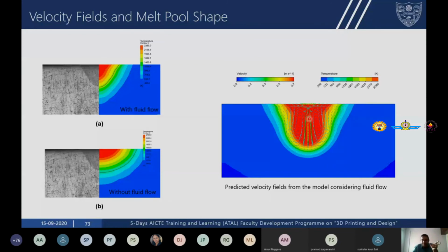Let me explain this once again. If you have a negative temperature coefficient of surface tension, then you're going to have a flow from the center to the edge, then downwards. In that case, you're going to have a melt pool that is shallow and wide. If you have a positive value of temperature coefficient of surface tension, the flow occurs from the edge toward the center, downwards and up towards the center. In such a case, you have a deeper and narrow melt pool. So the importance of considering fluid flow and surface tension effects is apparent from these simulations.